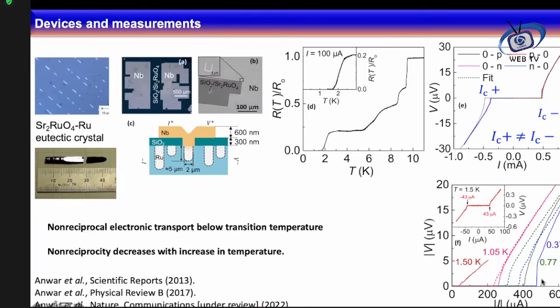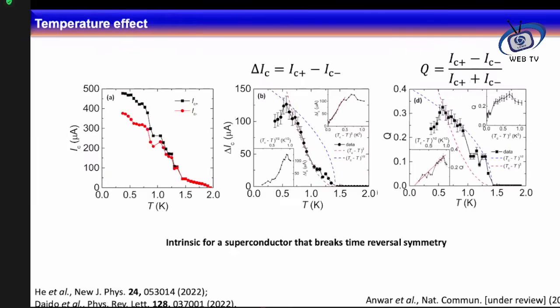And then the other interesting thing was that if we increase the temperature, meaning that we are weakening the superconductivity, we are moving toward its superconducting transition temperature, where it will actually switch back to the normal state, this effect is suppressed. And then a very clear message here is that this superconductor, which is an unconventional superconductor, exhibits non-reciprocal transport, that is in fact the diode. And this diode effect is suppressed with the increase of the temperature.